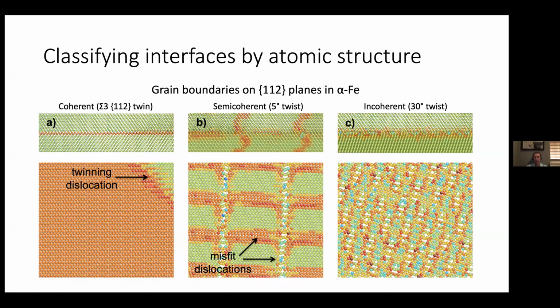If I were to take this coherent twin boundary and change its crystallographic character just a little bit, so take the top grain, for instance, and rotate it a little bit, let's say by 5 degrees, around an axis that's perpendicular to the grain boundary plane. So I'm just going to do a relative twist of these two grains by 5 degrees. As soon as you do that, the structure of the interface changes. So here's the plane again, okay? And just looking at it, you can see that it's not nearly as flat and sort of strain-free as the one on the left.